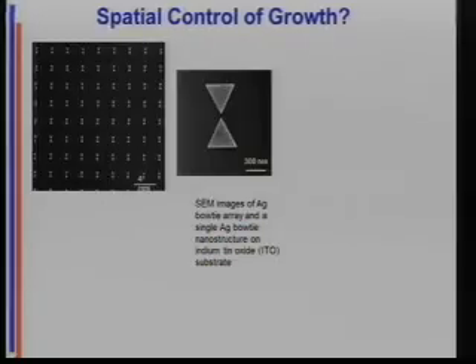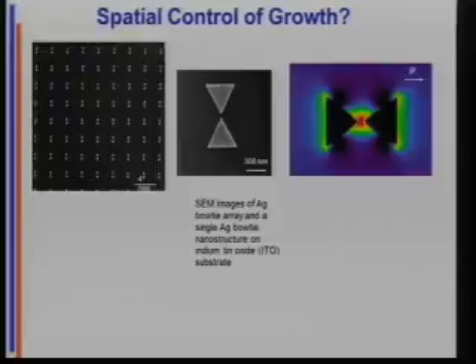It's cool as a deposition method, but spheres aren't very interesting. These are more interesting. This is a substrate covered with silver bow ties that David Wei's group made with electron beam lithography. And this is a single bow tie, okay? Now, when you look at the surface plasmon resonance, if you calculate where the EM field should be, and I have to thank George Schatz at Northwestern for doing this calculation, it should be concentrated in the middle. And so now, if you can get the deposition to follow where the EM field is, you have a way of soldering that bow tie together.